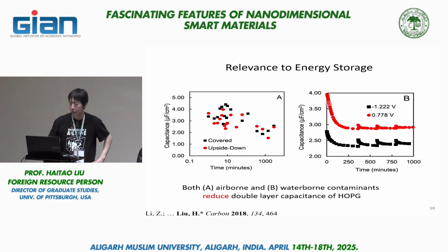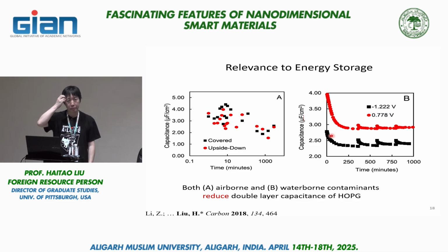So what we did is we do the measurement continuously, and then at here, we stopped the measurement. Instead, we apply minus 1.2 volt and hold it for some time, and then we resume the measurement. When we resume the measurement, we find, oh, we have some recovery. But then it got declined again. So it looks like we can get rid of some of those contaminants, but not 100%, obviously. And also, it goes back to the contaminated state pretty quickly as well. So some effect, but not very promising.